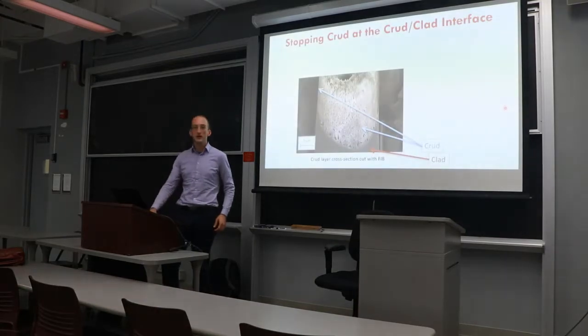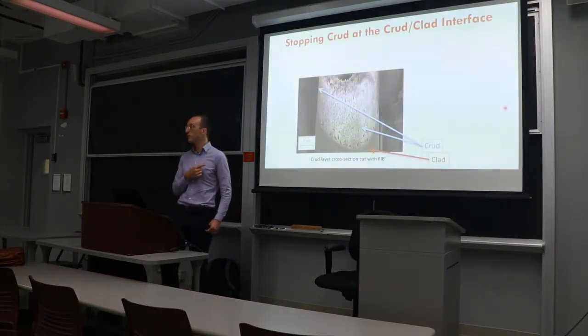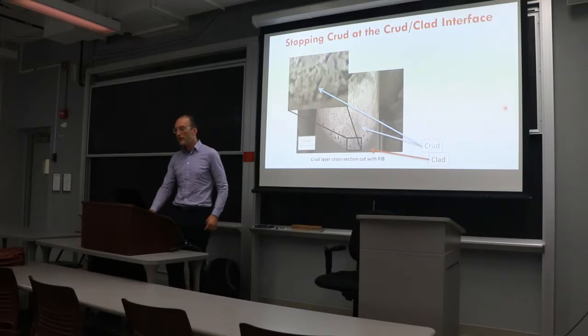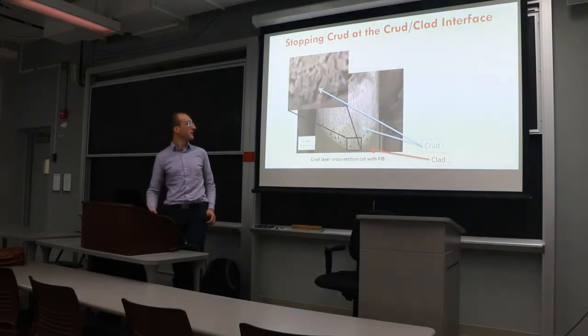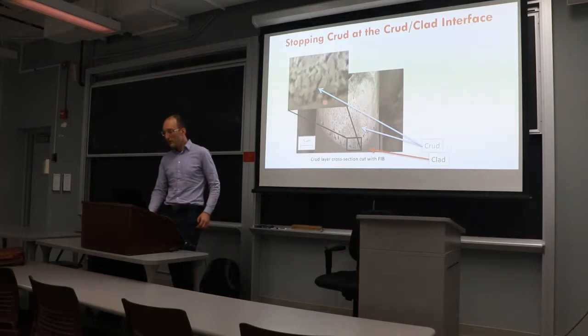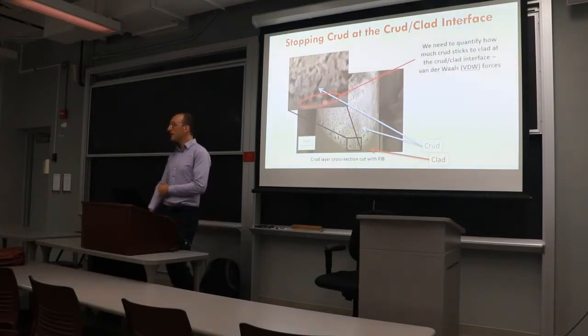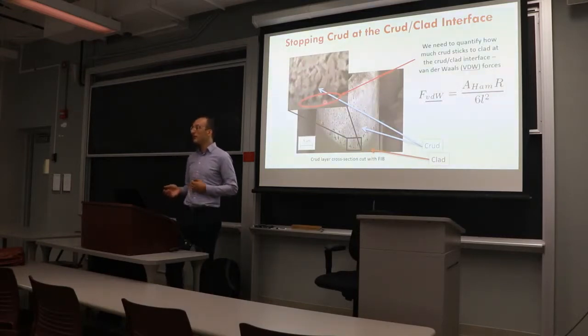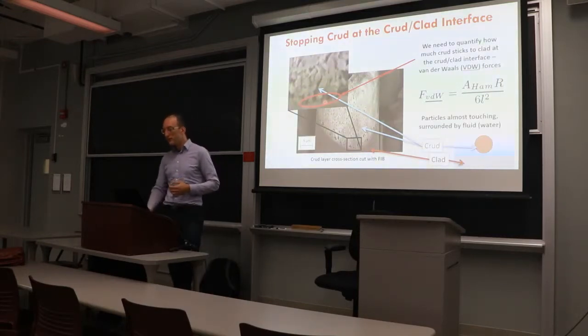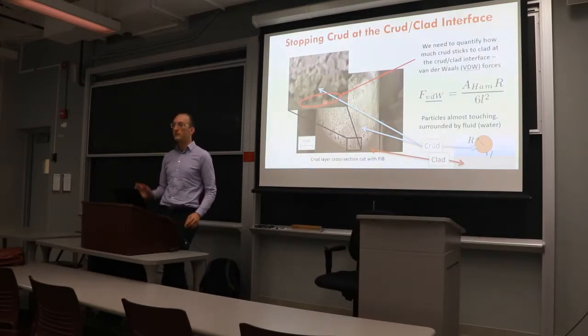So we would take particles of crud, which we grew in one of our loops that we'll show you in a bit, and focus right in on the interface to ask, what makes this particle stick to that cladding? That's what we really want to know, because if we understand the sticking mechanism, we can design materials against it. There's a simple equation relating the van der Waals force between a sphere, which we'll call the crud, and a piece of cladding, based on the sphere's radius and the distance between the sphere and the cladding. Anyone know why the distance never goes to 0 and the force never goes to infinity? Why can't anything ever touch anything else?